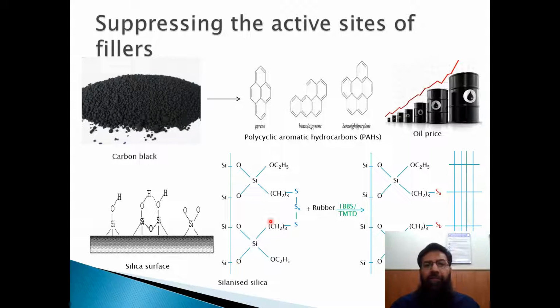So if we treat it, then after treatment this silica would be a better filler as compared to carbon black for the reinforcement of rubbers and polymers. And the activated silica, or the silane treated silica, would give us better mechanical performance and better dispersing properties as compared to the normal non-treated silica.